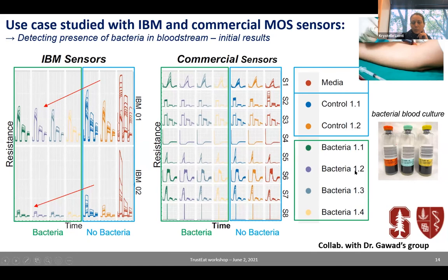Of course, what we want to see is that when there is a presence of bacteria, we want to see a change in resistance shown by the sensors. And this is precisely what we see with our IBM sensors. As you can see, without bacteria, the resistance level is much higher than with the bacteria. Whereas for all the commercial sensors, and there are 8 of them in that nose, the response is pretty much flat. Bacteria, no bacteria, we don't see much of a difference.